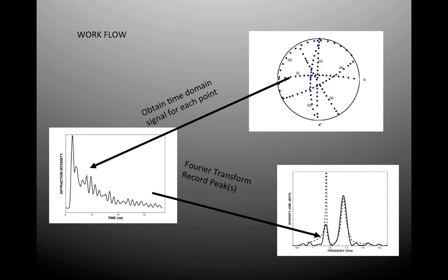Now, the true Rayleigh wave has a very narrow width in the calculations that is widened for the time window data that we use. The dashed line represents a theoretical calculation from Green's elastic tensor with the appropriate elastic constants adjusted such that we do fit these peaks. And you can see that the theory matches the experiment quite well.